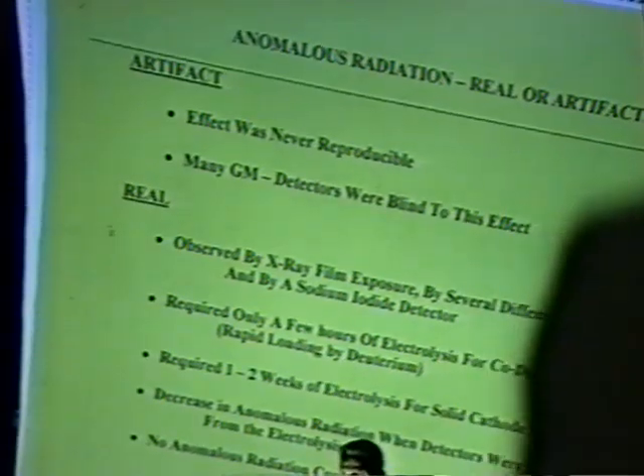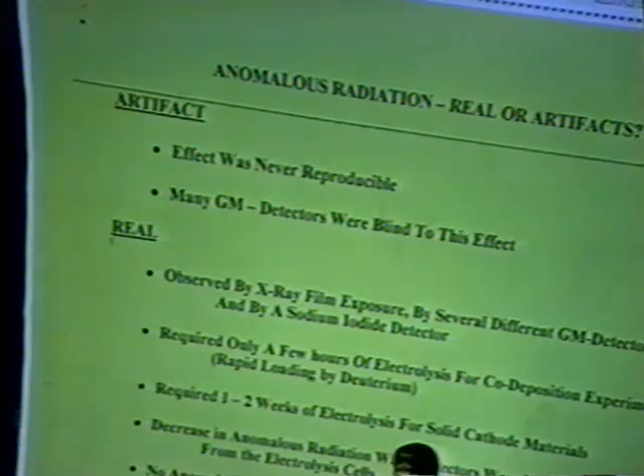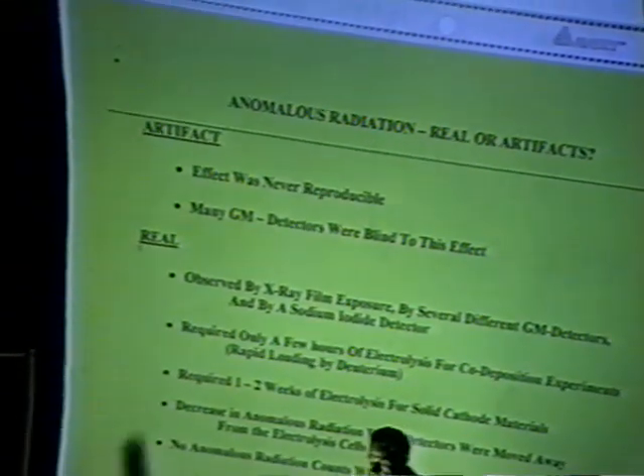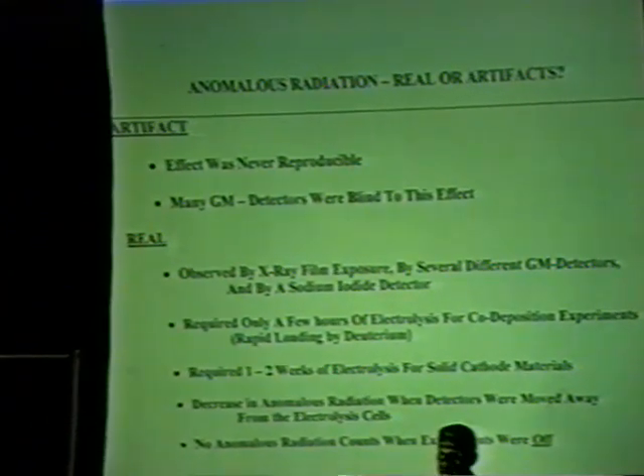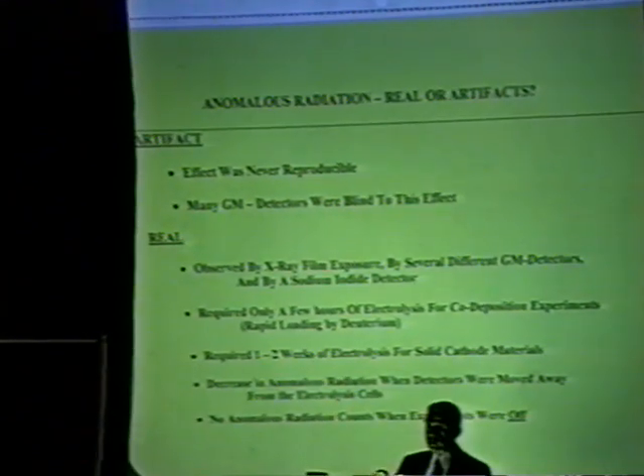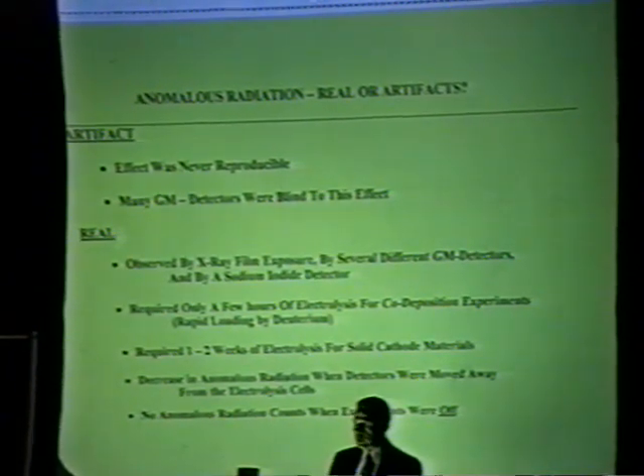So you can come by the poster. We have other examples with other detectors, also sodium iodide detectors. If we had a solid electrode, we would see this effect also, but it took maybe 1 or 2 weeks before the radiation would show up. Co-deposition would appear almost immediately, within the first 12 hours. But with a solid rod, where it takes longer to load, it would often take 1 or 2 weeks before the effect would show up.